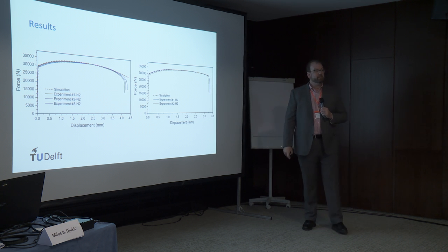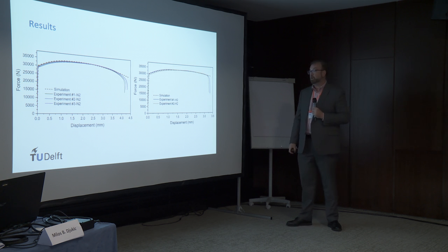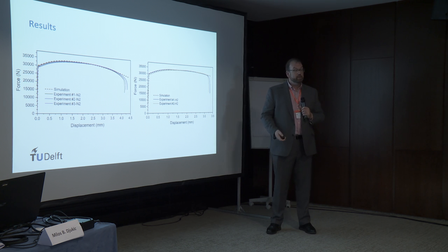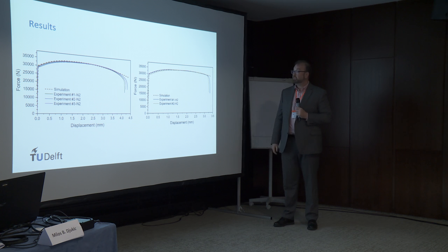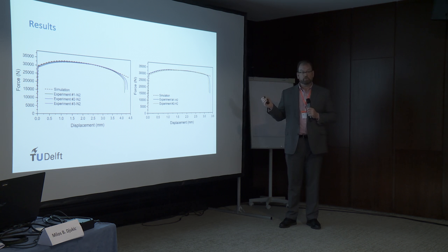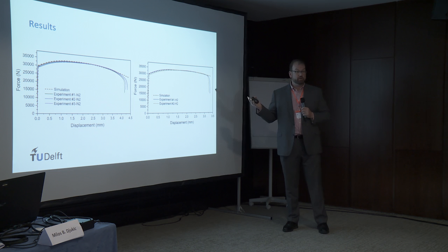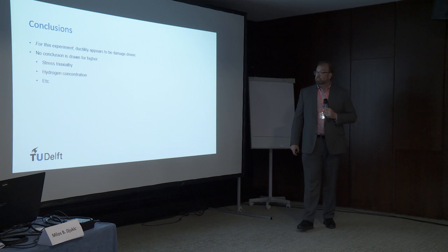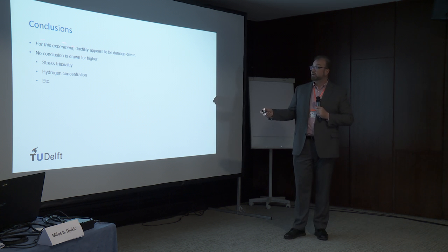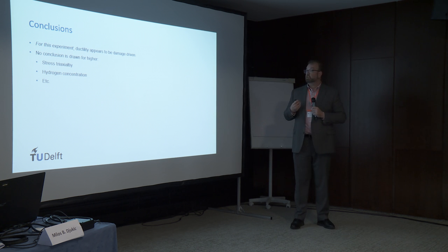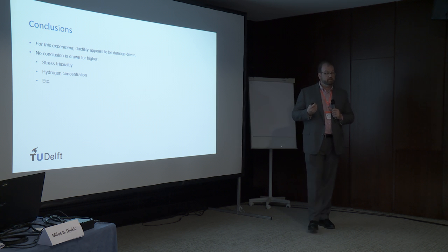What disappoints me is that this good correlation was achieved with exactly the same true stress-strain curve for both the nitrogen-loaded and the hydrogen-loaded experiments. So, at least for this experiment, we can say that all of the reduction in ductility was due to a reduction in the local failure strain — or, in the case of transgranular quasi-cleavage, that there was an imposed fracture stress in the hydrogen-loaded specimen.